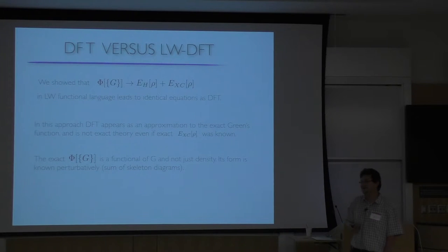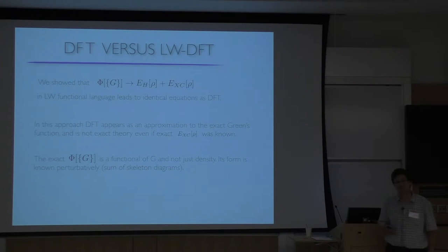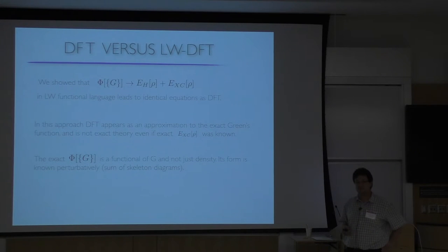Well, the only explanation is that the correlations are local. You can see this in any example you wish. Correlations are pretty local in space, and therefore a local ansatz is expected to be reasonable. Now, the fact that a completely local ansatz, just LDA, is so good is a big surprise in my opinion. I wouldn't expect that. I would say that locality in real space shouldn't be exactly locality to a point, but locality in some larger region. But it turns out in practice that it works so well, at least for weakly correlated systems. The band structure agrees with experiment very well.